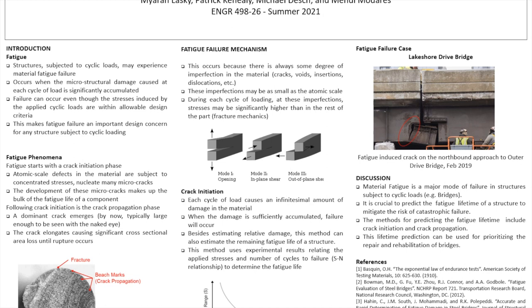Because cyclic loading causes damage to the material until failure, the crack initiation method can be used to estimate both relative damage as well as remaining fatigue life. Using an experimentally obtained SN curve, or stress range to cycle relationship, we can quantify the likely number of cycles that will occur before failure at particular levels of stress range. Using this information in combination with real-time data, we can estimate at what point a sample is in its life cycle, as well as the remaining fatigue life. A typical SN curve is shown below in the middle, with stress range plotted on the y-axis and cycles plotted on the x-axis.